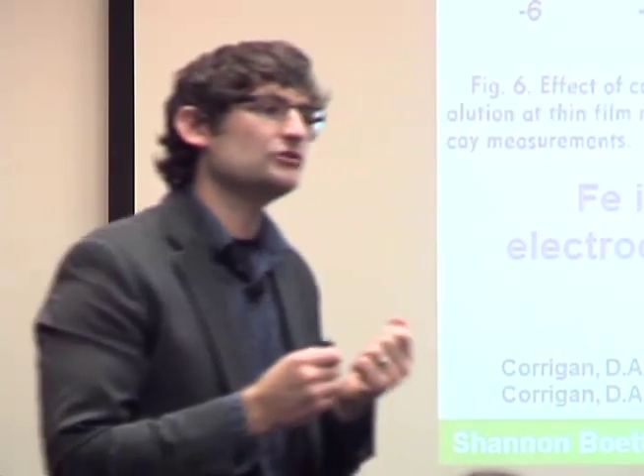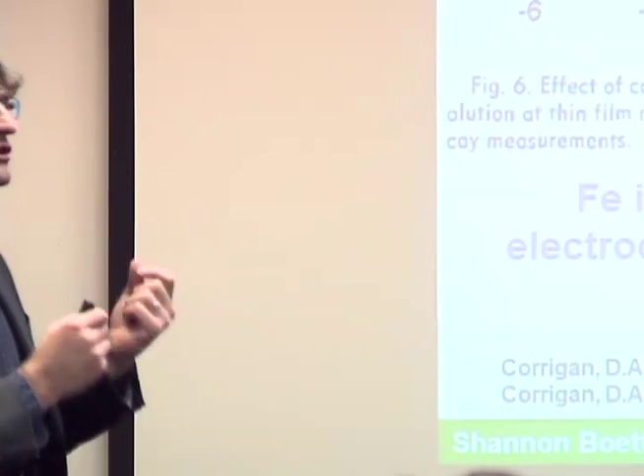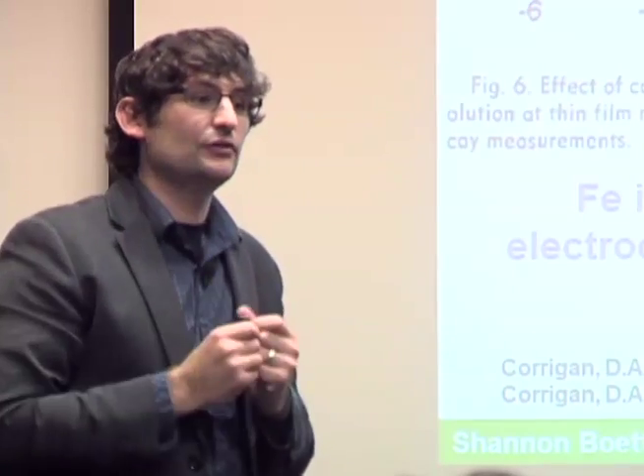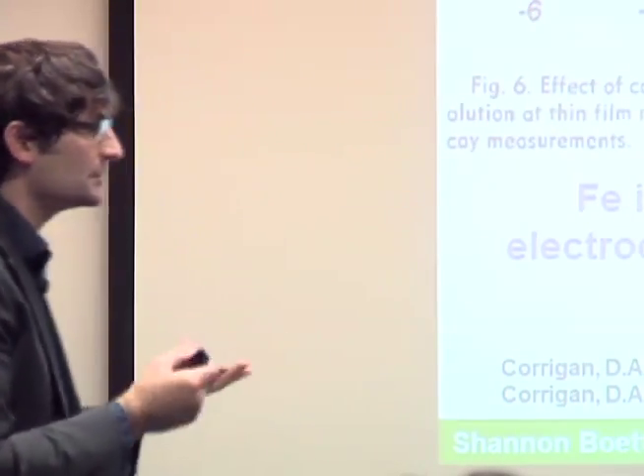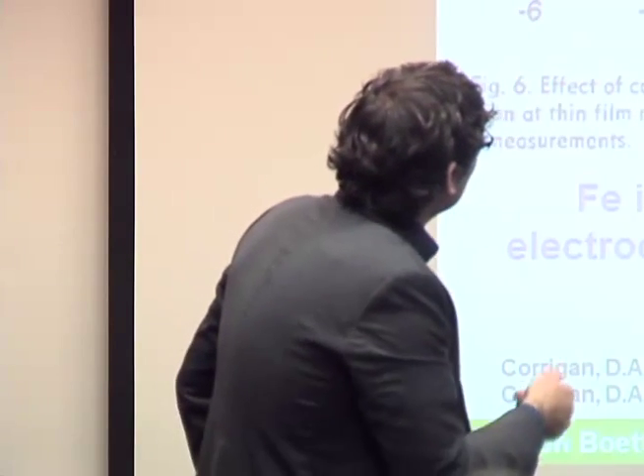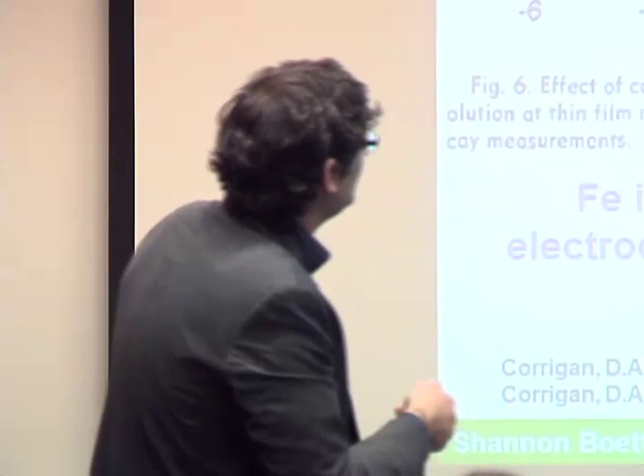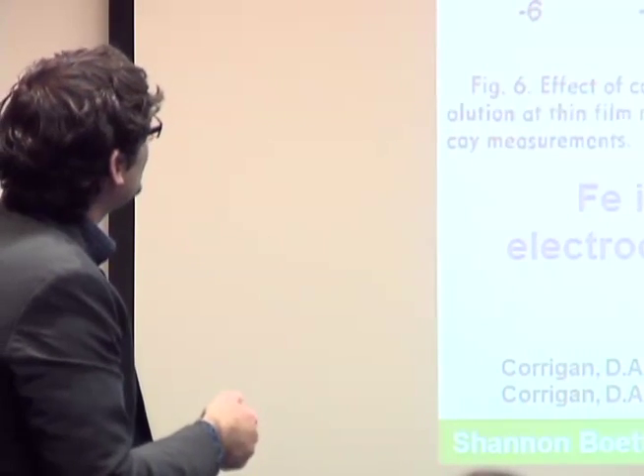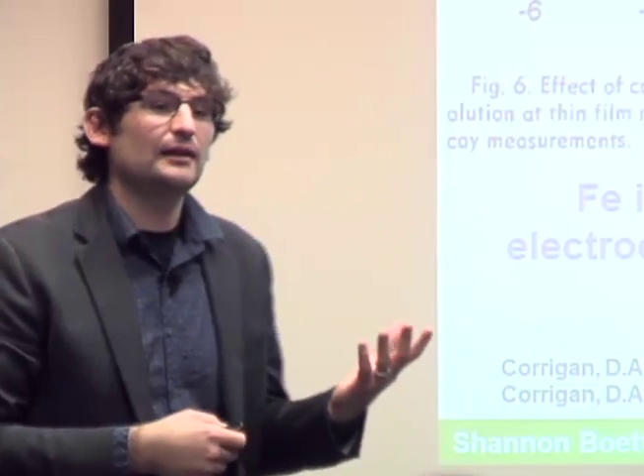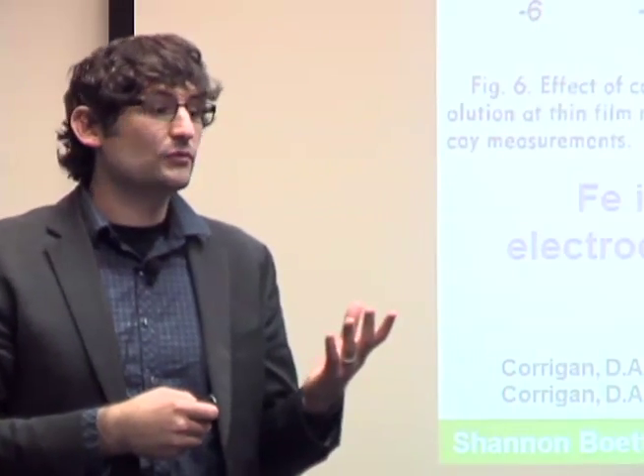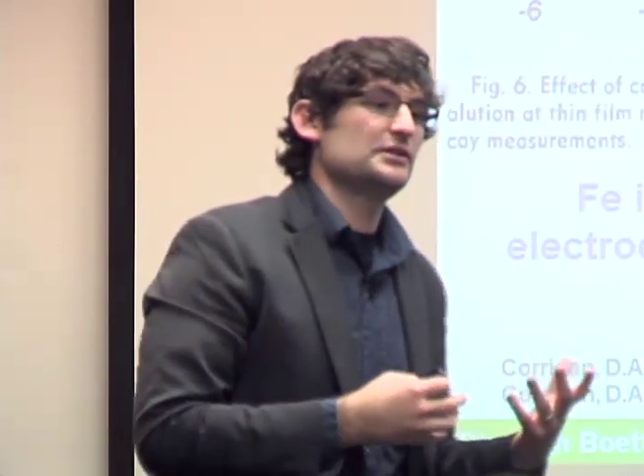He was basically trying to make a reproducible nickel hydroxide electrode, but every time he made one, he'd charge it, and it would discharge by itself, at a different rate each time. So he had a very hard time making a reproducible electrode. What he found is that the charged nickel hydroxide was making oxygen, so it was driving the oxygen evolution reaction, which is what you don't want in a battery. Of course, it's a self-discharge pathway. He traced this to iron impurities in his electrolyte. So iron had a significant effect on the electrocatalytic activity. He didn't fully understand what it was doing, but it was affecting the rate of self-discharge in these batteries.